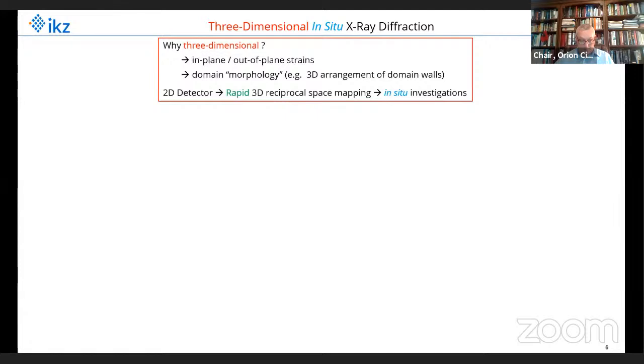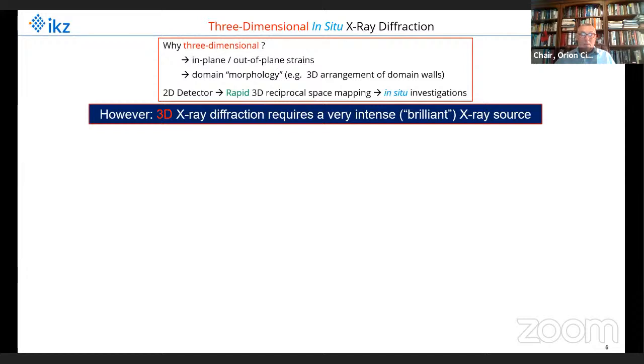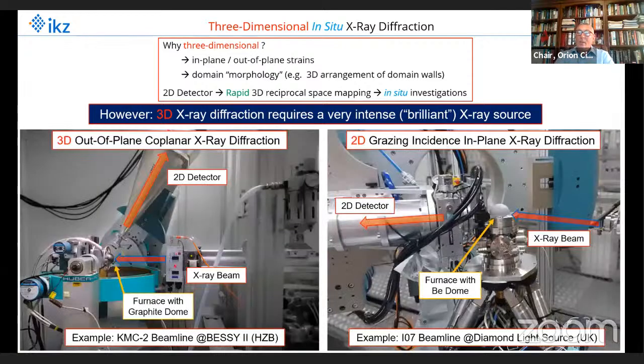In order to do this in a rapid way, we have used a 2D detector, and then it goes so fast that we can even do in situ investigations, because one 3D reciprocal space map does not take too much time. Of course, for these studies, we need a very intense X-ray source, so we have to do all these experiments at synchrotron radiation facilities. And at the bottom, you see 2 experiments, exemplarily one at BESSY II at the left side, and one at the I07 beamline at the Diamond Light Source in UK.